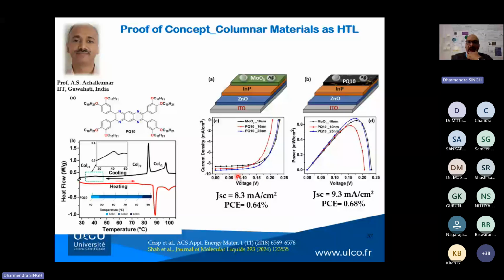And here is the structure of a quantum dot based solar cell device, in which he used ZnO, InP and MoO3. MoO3 is used as the hole transport layer material. Crup and his colleagues showed that this device has a short circuit current density of around 8.3 milliampere per centimeter square, and the PCE for this solar cell device was 0.64%.